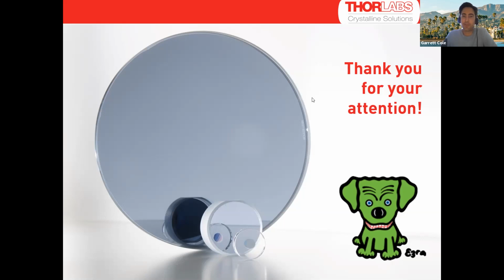And point 2, are you concerned about delamination from the substrate over temperature? Yes. So these materials have relatively high coefficients of thermal expansion, about 6 parts per million, if you know these numbers. It's actually matched to sapphire, which is kind of interesting. So for fused silica, that's a huge mismatch because fused silica is sub ppm expansion. So yeah, we can operate at room temperature, but with fused silica, for instance, we can't heat those optics above 150 Celsius or they start to delaminate.